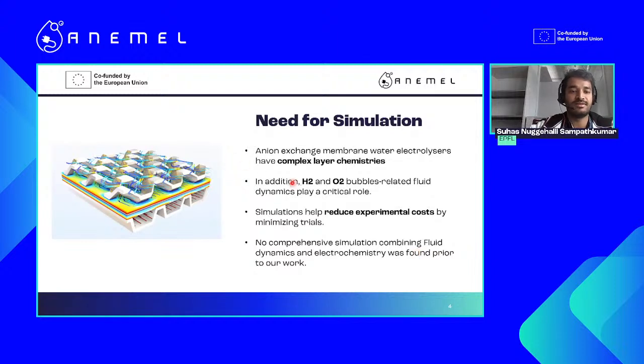And then why is there a need for simulation? Because, as you see, these layers are complex, and there is an interconnection between the bubbles evolved due to water splitting, because hydrogen and oxygen evolve as bubbles. And then you also have some chemistries happening in these layers which help in splitting of the water, which are complex to explain. So the simulations can couple the fluid dynamics associated with the bubbles and the electrochemistries, which are largely defined by theories, and then identify performances, which can help reduce experimental cost, because assembling and creating new layers is pretty tricky and expensive.